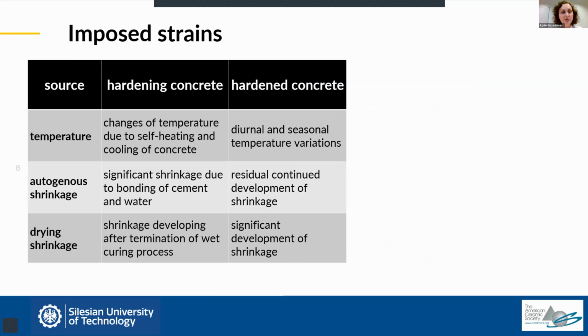First of all, we must remember that cement hydration is a highly exothermic process, which means that during this process, large amounts of heat are produced, which lead to an increase of the temperature in the element. Moreover, hydration of cement, so bonding of cement with water, causes the so-called autogenous shrinkage, which means that the volume of the product, the cement matrix, is a little bit smaller than the total volume of water and cement. This is another reason why we have a decrease in volume. Finally, some of the water which we add because of workability requirements is not needed for the hydration, and this water is removed due to drying shrinkage.